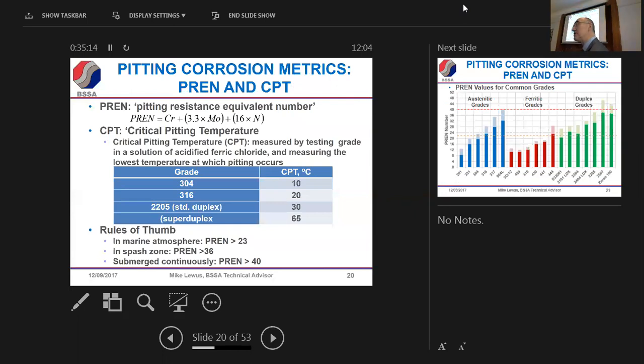There's also something called the critical pitting temperature, the standard corrosion test, as no doubt some of you, if not all of you, appreciate. The critical pitting temperature is simply immersing a coupon of stainless steel in a quite aggressive oxidizing medium for a particular time, at a particular temperature, and then taking it out and counting the number of pits per square inch or centimetre, how deep they are, and what sort of morphology they've got.